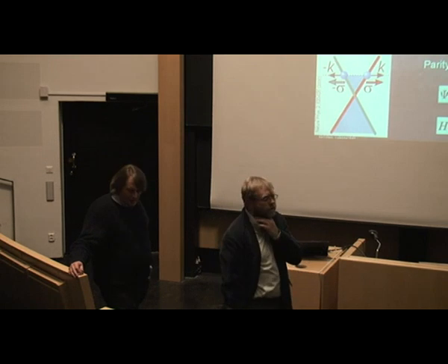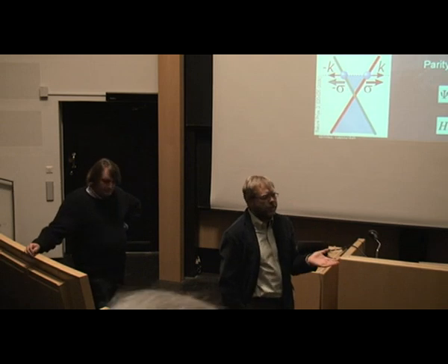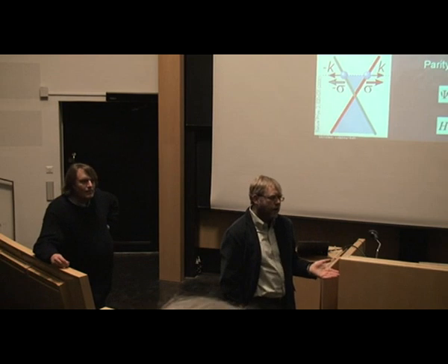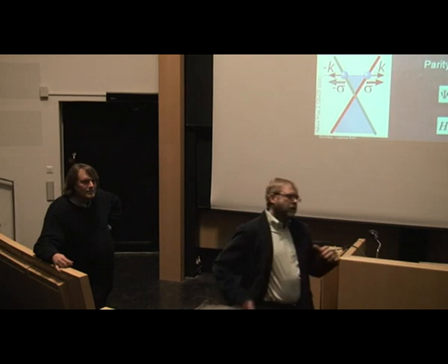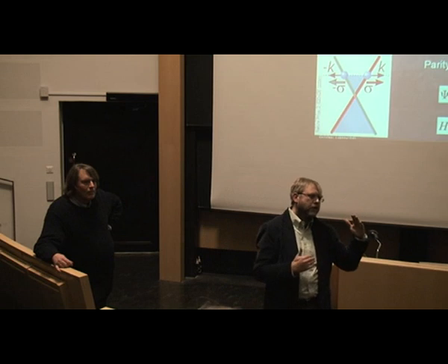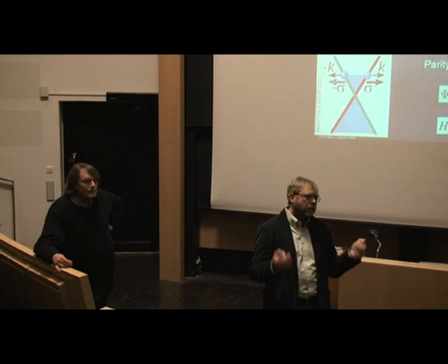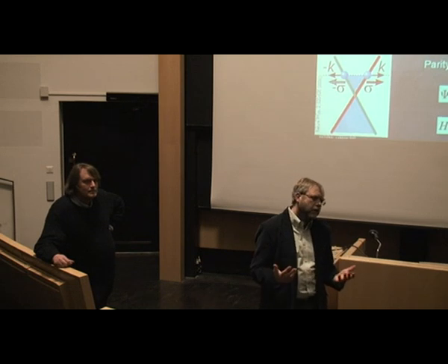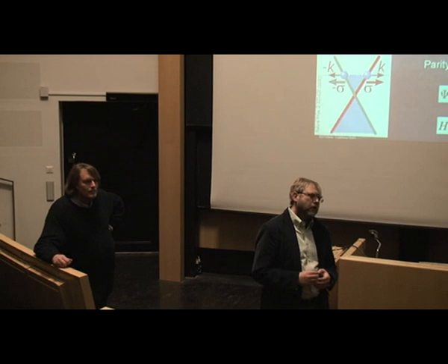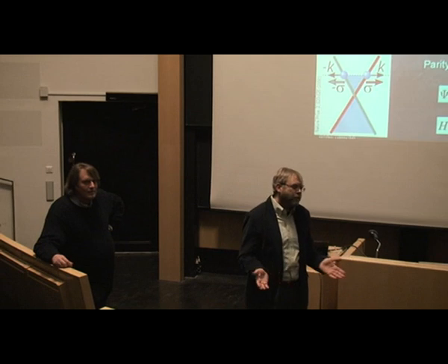Wallace actually died last year, I think. But in 1948 he published a PRB where he did the band structure essentially of graphite, with gamma 1, gamma 2, whatever the nomenclature is, gamma prime, gamma double prime, etc. But as a build-up for that, he showed the band structure for graphene. He showed that with just a tight-binding Hamiltonian, you can see this Dirac, linear spectrum at the corners of the Brillouin zone. The hexagonal lattice in real space is replaced by a hexagonal lattice in reciprocal space, and he showed that the spectrum vanishes there. It was an interesting observation, a very interesting theory, but nobody latched onto it because there was no real material that would support this kind of band structure.